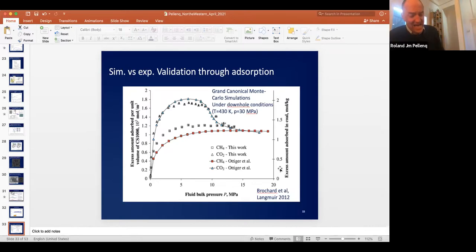Okay. So just a comment, you see that the CO2 actually has a cusp-like shape. It's because we are plotting the excess adsorption isotherm, which is what we compare with experiment. Experiment always measures the excess adsorption. Excess with respect to what? To a box of the same volume containing no porous material. So this is the effect of the confinement, if you like. And we have a cusp because at this high temperature we are supercritical in the case of CO2, and the density outside is larger than the density inside. That's why you have this cusp. But anyway, we can predict the adsorption.